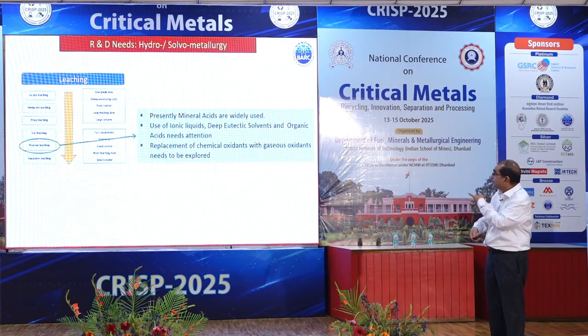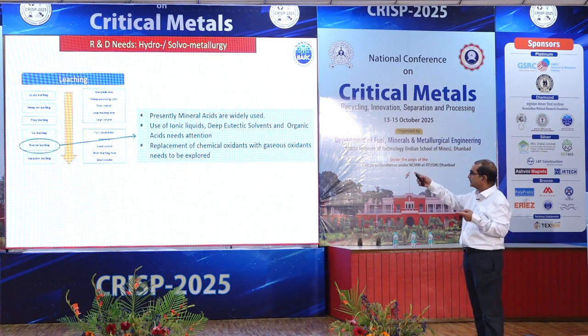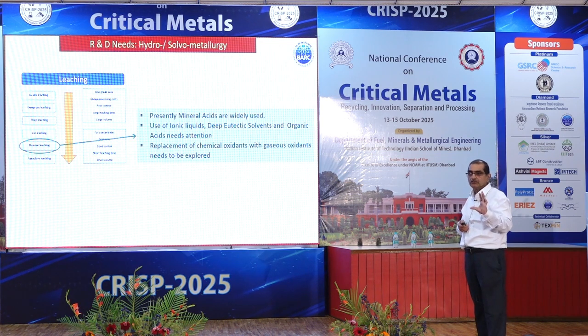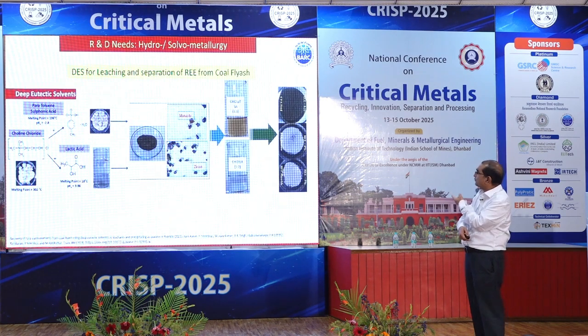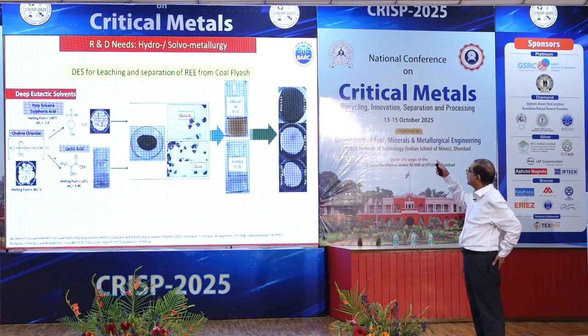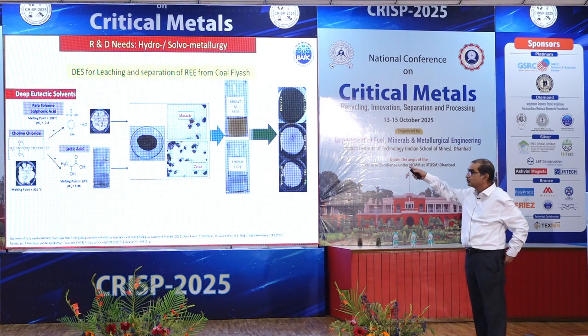When you come to the stirred reactors, that is reactor leaching, we have to replace the mineral acids very strongly. We should try to use ionic liquids, deep eutectic solvents and organic acids. They need to get the required attention. And then replacement of all the chemical oxidants with gaseous oxidants. Oxidants like oxygen, ozone, hydrogen peroxide will do the same job like other chemical oxidants. So we need to replace them with these. Now, in our own lab, we have conducted some studies on coal fly ash and how to recover the rare earths from that using the deep eutectic solvents.